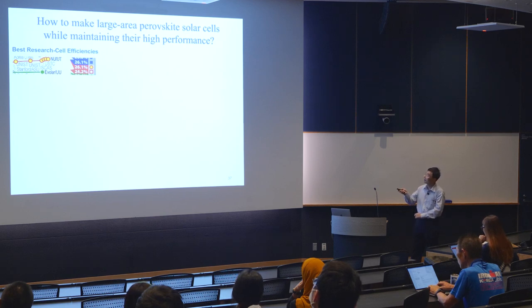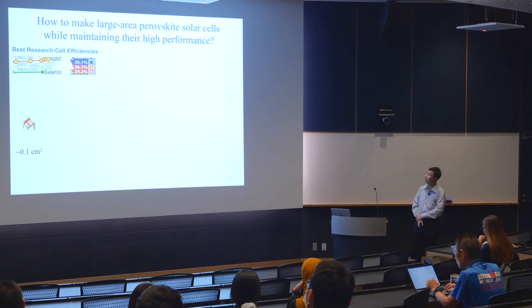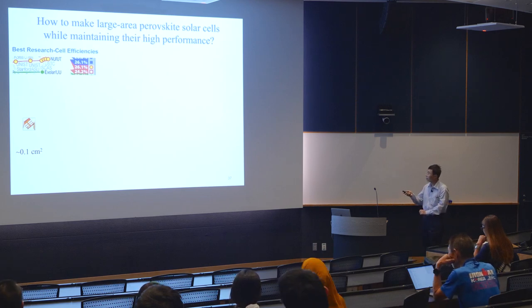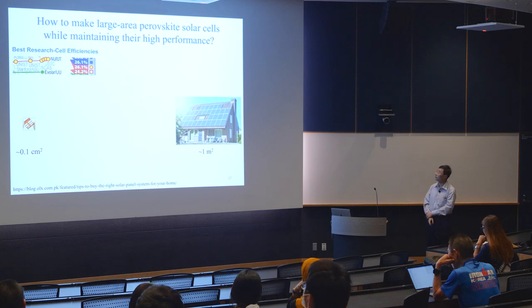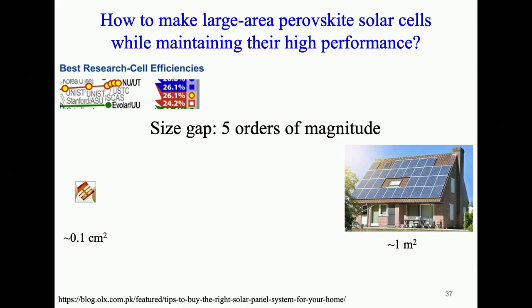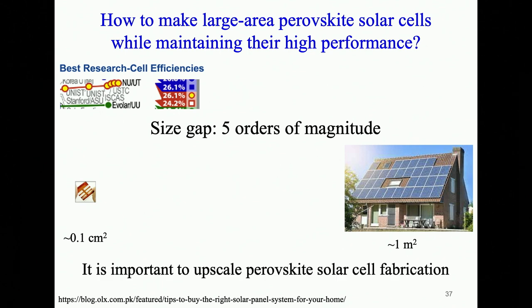But please note that this high efficiency is only achieved on a small area research cell with a typical size of about 0.1 centimeter square or even smaller. On the other hand, for practical applications, a size of about 1 meter square is usually required. So here we see a size gap of about 5 orders of magnitude. That is why it is very important to upscale perovskite solar cell fabrication.